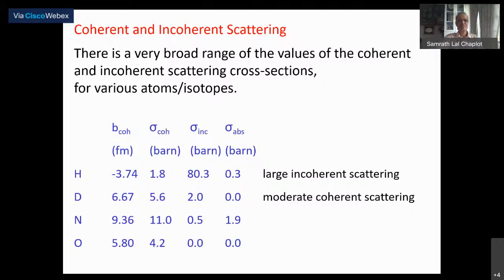So that's a very important technique used involving deuteration of samples. Of course, other atoms are there. We are often also interested in oxygen diffusion, or for example, lithium diffusion in lithium-ion batteries, or sodium diffusion in the new sodium-ion batteries. There, the cross sections involve both coherent and incoherent scattering, and so one has to effectively analyze the data, and of course the signal would be much weaker compared to what you observe in hydrogen.